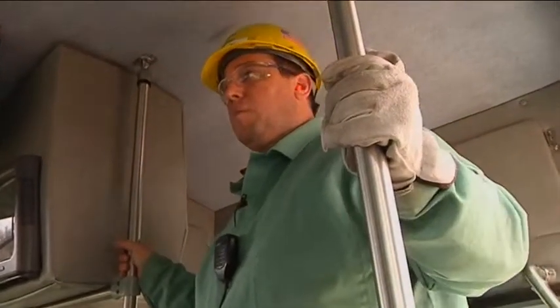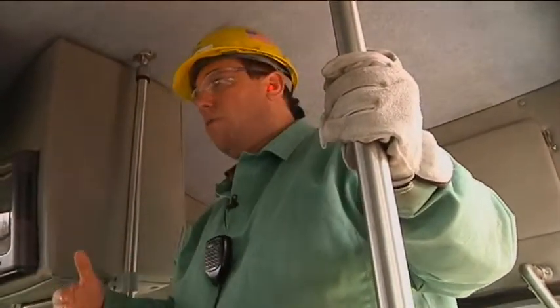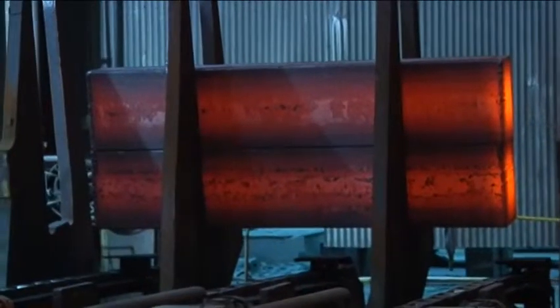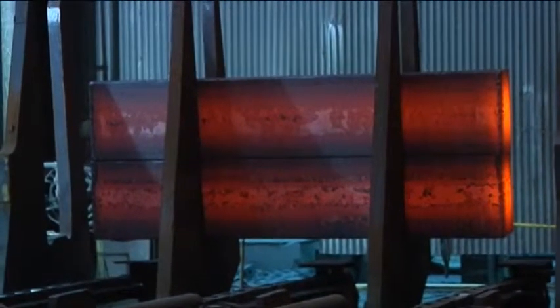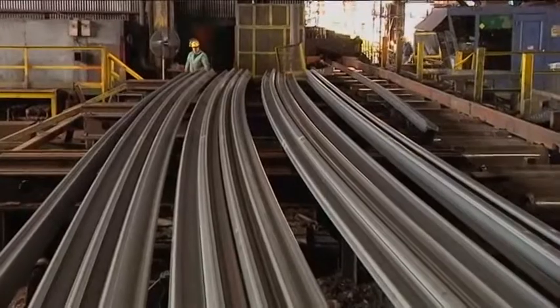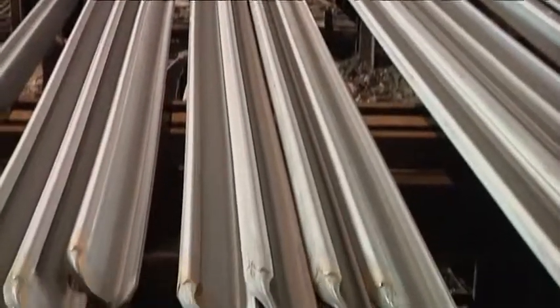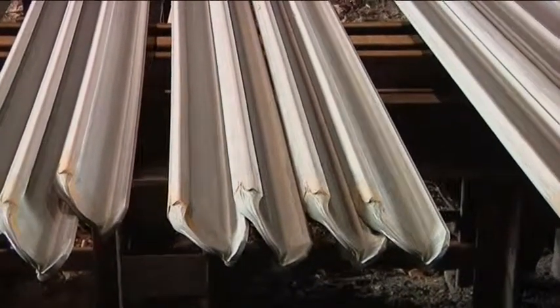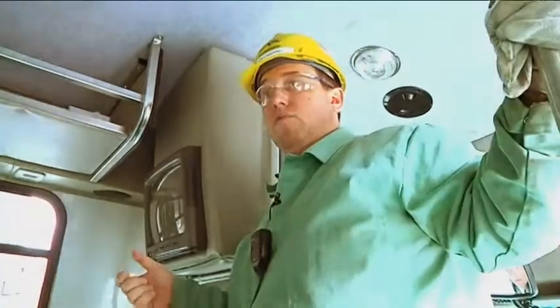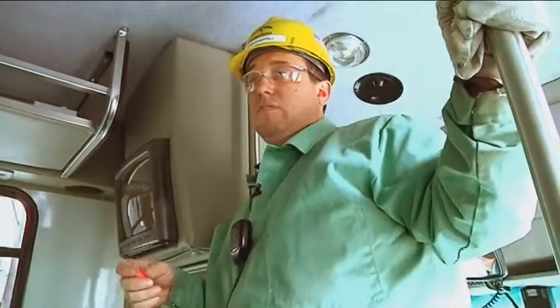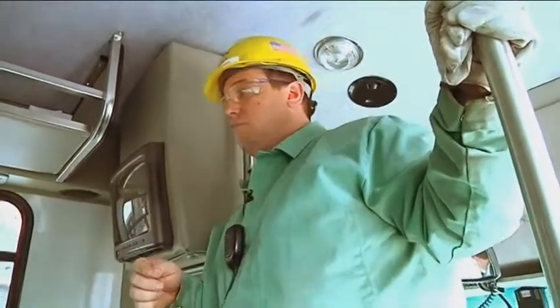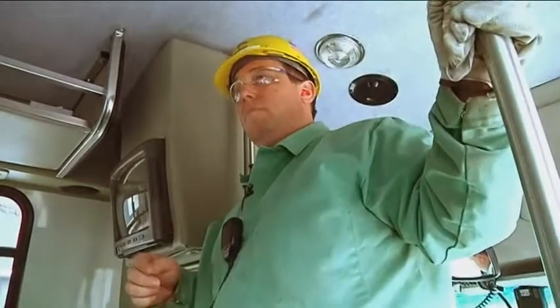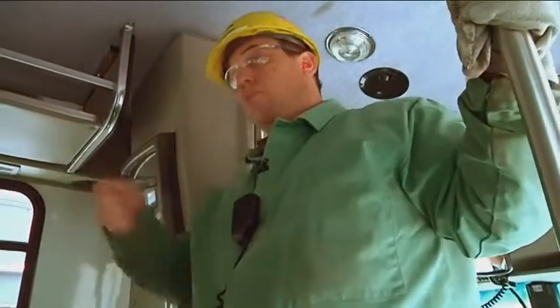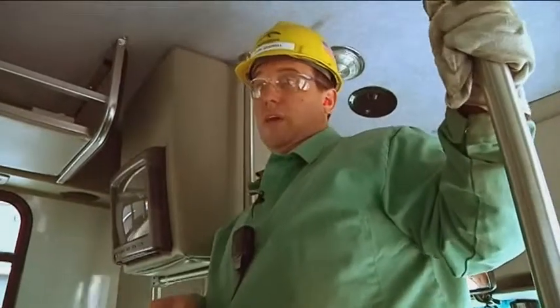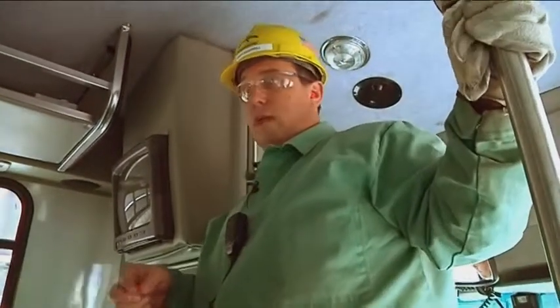Most of when we make rail, we cut a bloom to a specified length that produces 4 rails about 90 feet long from one as cast bloom. To get back up to rolling temperature, about 2100 degrees, takes 5 to 6 hours in a soaking pit set at about 2400 degrees Fahrenheit. If you let that bloom go cold, it takes about 14 hours to get it hot. And a whole lot of natural gas, right?